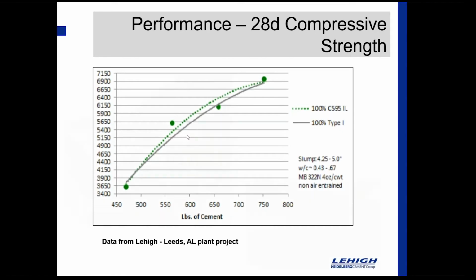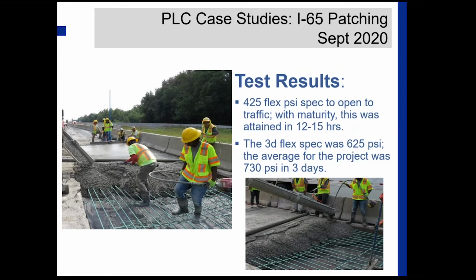A little closer to home, we had a project back in September of 2020, just a few months ago, on I-65 patching, where some Portland limestone cement was used, and that with some good performance, I think. So we saw a 425 flex PSI spec to open to traffic with maturity that was reached in about 12 to 15 hours. The 3-day flexural spec was 625, and the average for that project was about 730 PSI in the 3-day break. So again, I think you see a little bump on that early side that tends to be very beneficial with the Portland limestone cement.